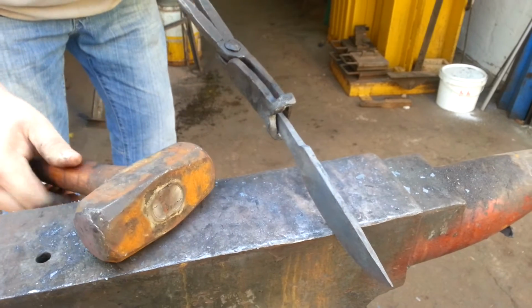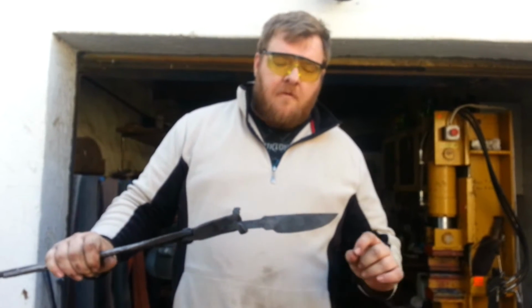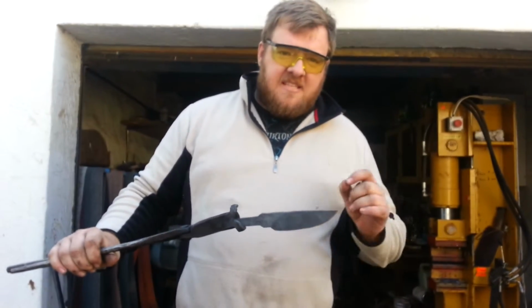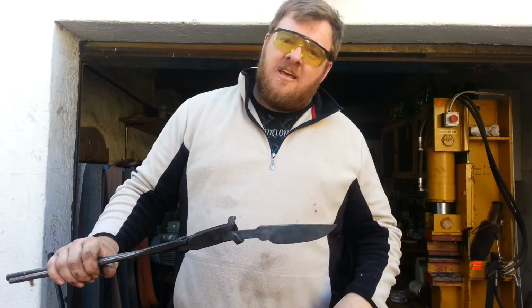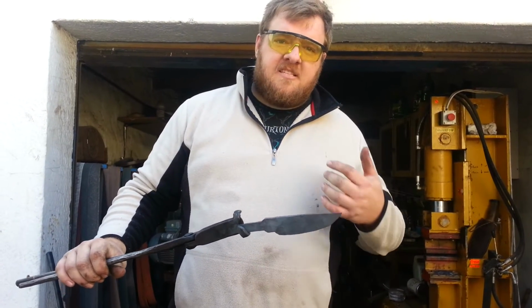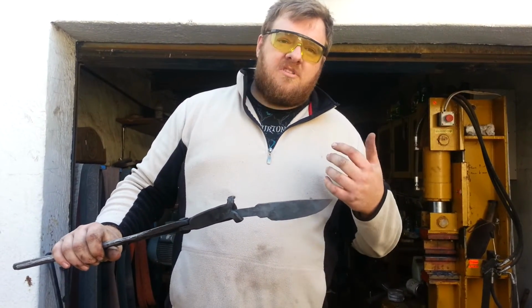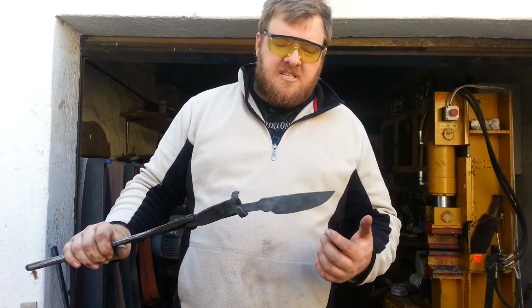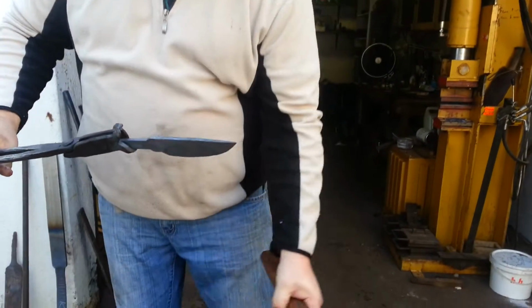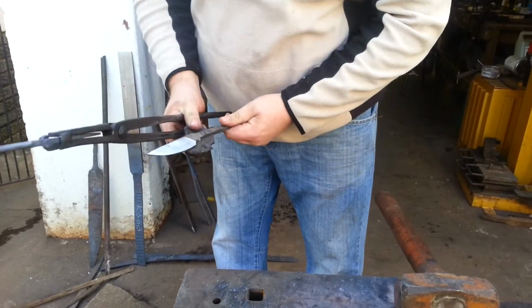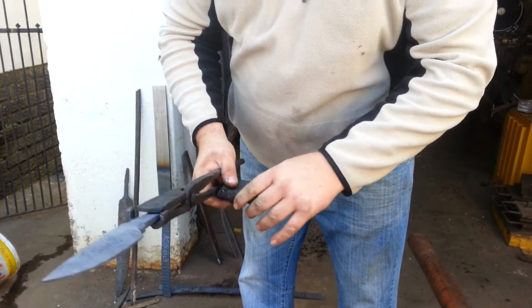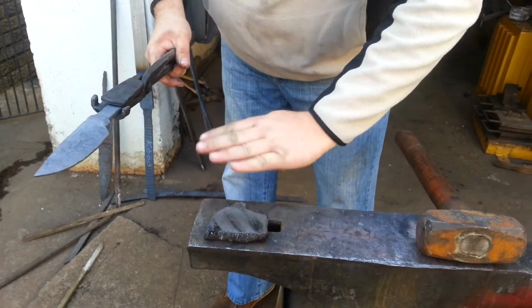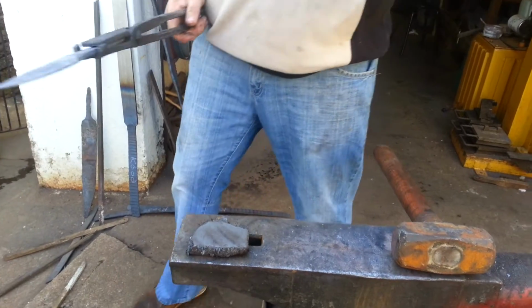Perfect. I'm going to normalize the blade once. Normalizing is de-stressing from the forging process. We heat the steel till it becomes non-magnetic. Not too much higher. If you heat the steel too hot, it causes grain growth and crystal growth within the steel, which makes it brittle. So we're going to take the magnet here. And I'm going to run it over the magnet. Now you can watch me.